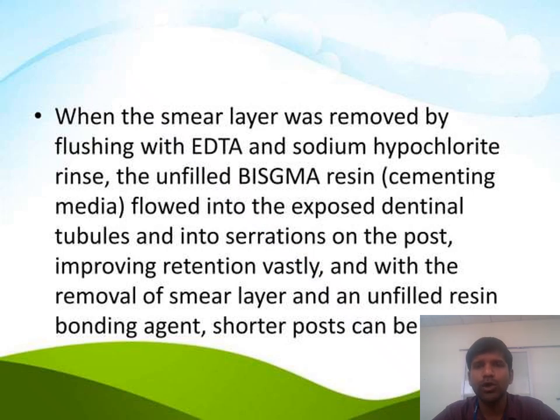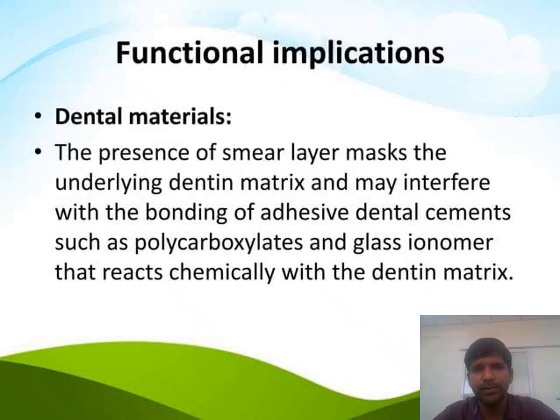When the smear layer was removed by flushing with EDTA and sodium hypochlorite rinse, the unfilled bis-GMA resin, that is the cementing media, flowed into the exposed dentinal tubules and into serrations on the post, improving retention vastly. And with the removal of smear layer and an unfilled resin bonding agent, shorter posts can be suggested.